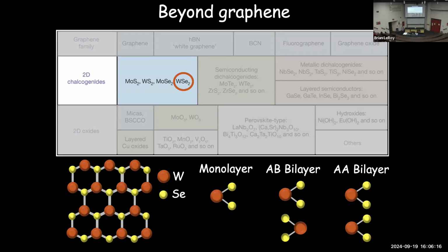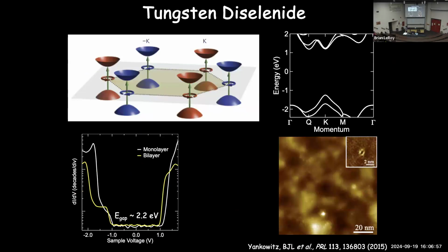But now there are two different ways to stack these materials on top of each other. We can stack them in this kind of AB configuration, where the top and bottom are rotated 180 degrees from each other, or we can stack more in this AA configuration, where they're pointing still in the same direction. In graphene, because from a side view the graphene is just a single carbon atom, there is no difference when you stack them. And so this actually is going to have an important effect on what the electronic states will look like in these TMD materials.